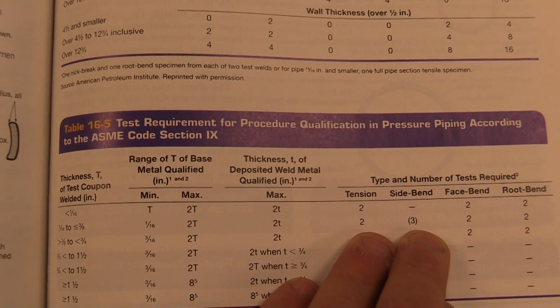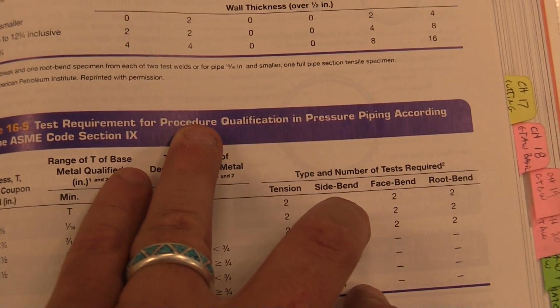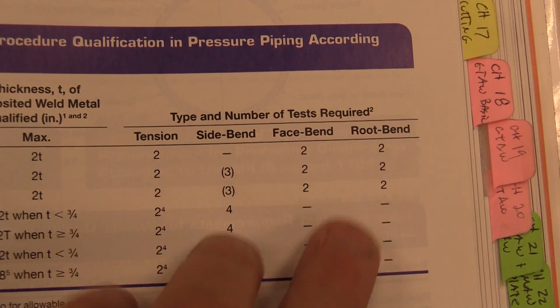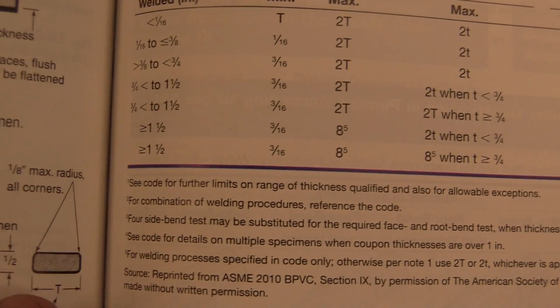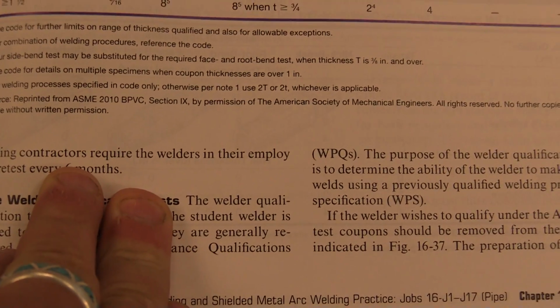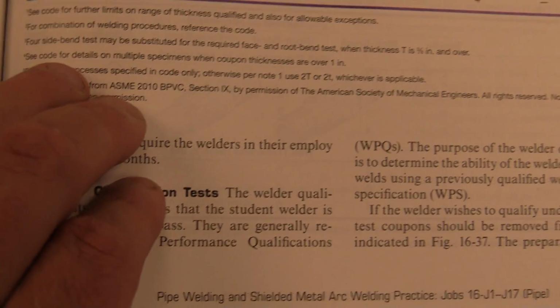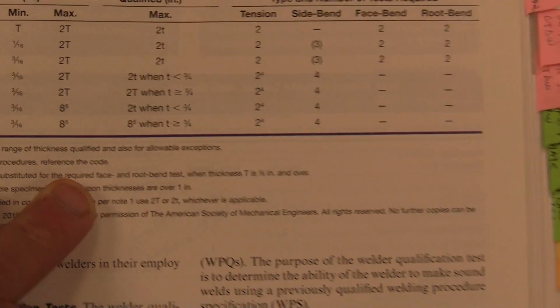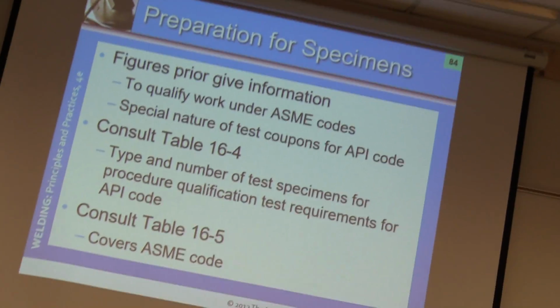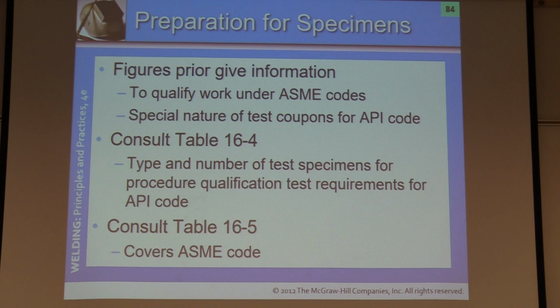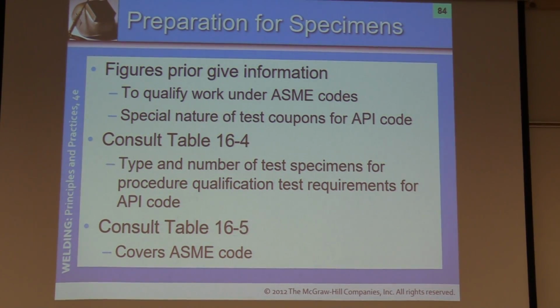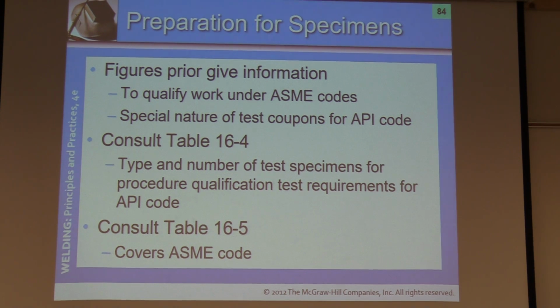How many bends should we do? So for a procedure, this is a PQR for procedure qualification, not welder, but procedure. You have to pull 2 tensiles, 3 side bends, 2 face bends, and 2 root bends. Now, you notice these are in parentheses. I told you the fine print gives you the detail. It says that 4 side bend tests may be substituted for the required face and root bends when the thickness is 3/8 of an inch and over. So, as you can see, reading technical documents is an everyday thing as a code welder. You do get to where you start to understand them. However, it can be very technical information.